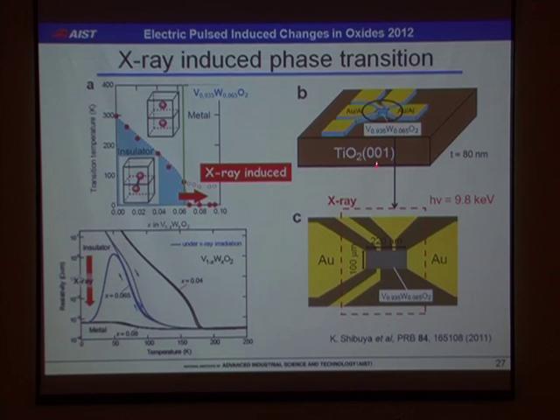And actually, we utilize this kind of configuration. Because the X-ray irradiation area is larger than that of the thin film surface, and the X-ray penetration depth is much thicker than the film thickness, we can discuss the resistivity or conductivity quantitatively. This is the advantage of using this kind of thin film.